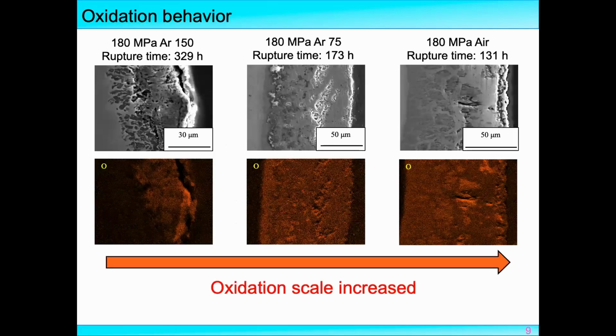Here we show the oxidation behavior. Only 3 typical testing specimens are given here. The test condition is given here. We can see that at the same applied stress level, all of the tests use the miniature specimen, at the same test stress level with different air flow: 150, 75, and 0.